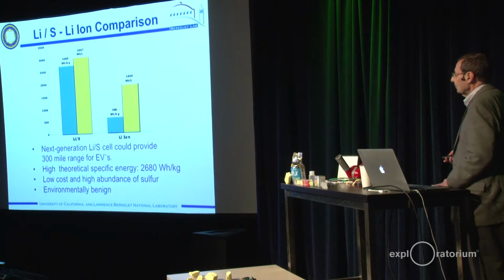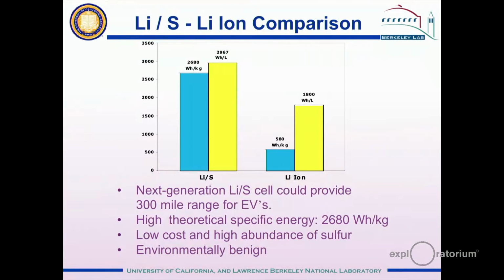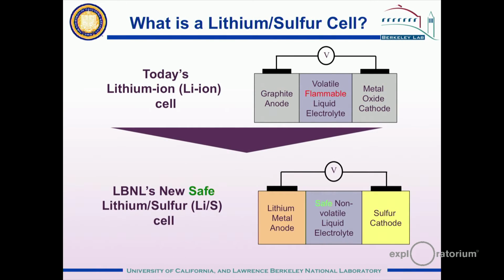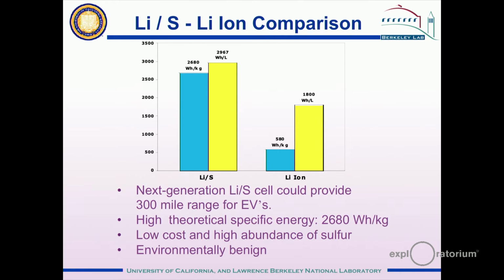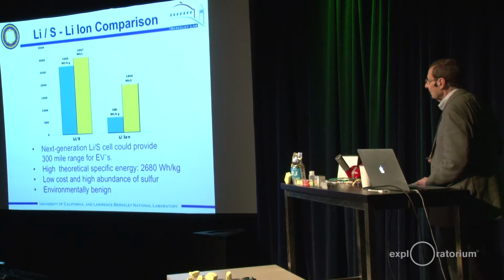So how do lithium-sulfur batteries compare to the lithium-ion batteries that we're all familiar with? In order to do this comparison, we have done some calculations based on the properties of the lithium and the sulfur. So the lithium sulfur battery can give us 2,680 watt-hours of energy per kilogram of lithium plus sulfur. The lithium-ion batteries that you're familiar with can give us a specific energy of 580 or so watt-hours per kilogram. So this is an advantage of more than a factor of 4. So that means that in your cell phone, you could operate the cell phone 3 or 4 times longer than you do now with a lithium-ion cell before you need to recharge it.